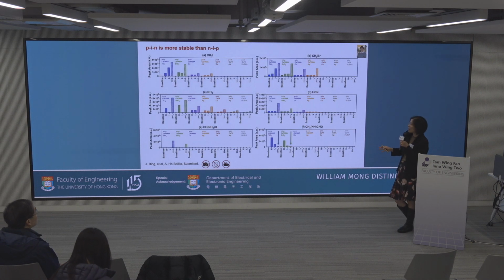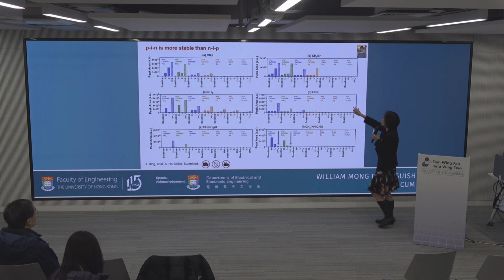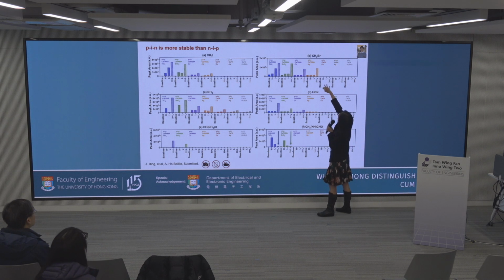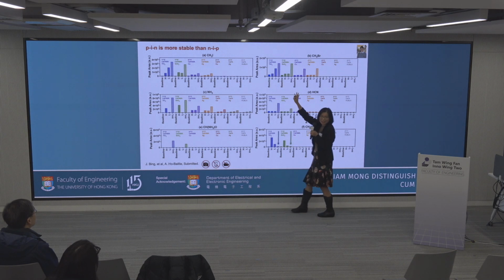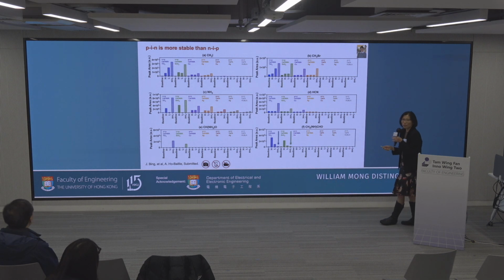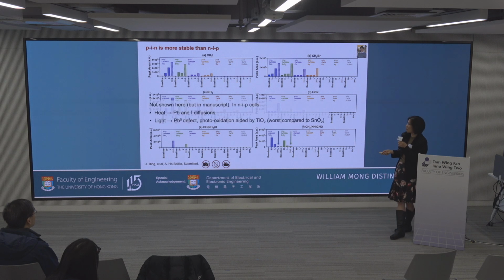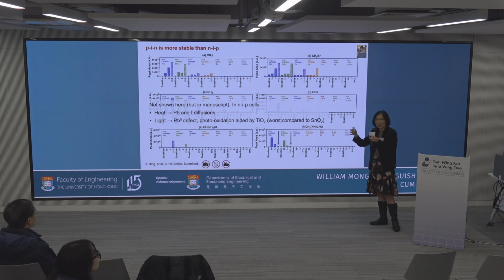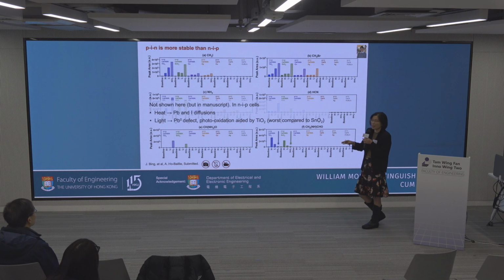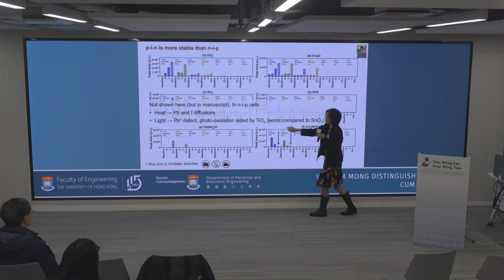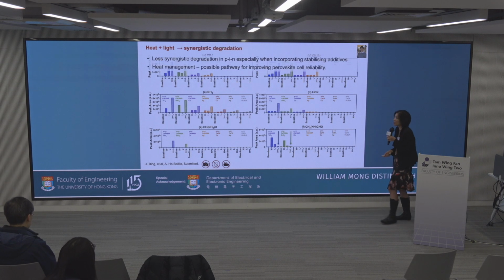But thankfully, PIN cells are more stable than NIP, so you can see the outgassing here. So these are all PIN cells. They are a lot less than the NIP. So thank goodness for that. And people can also see that when they just look at the cell performance. Not shown here, but shown in the manuscript, in NIP cells the heat drives the lead and iodide diffusions, whereas the light causes the lead zero defect at the interface. And it's really bad when you have the titanium dioxide compared to the tin oxide.